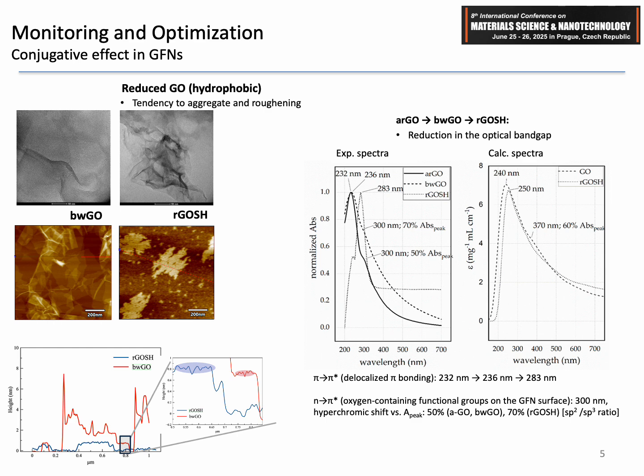This alteration, these spectral changes, can be related to two main factors: the formation of nanometer-size sp2 clusters and alteration in the linked chromophores, such as carbonyl or C=O instead of C-O bonds. What is more, the pronounced bathochromic shift to 282 or 283 nanometers that we observe for the reduced GO thiolated suggests the restoration of the pi aromatic domain, and the almost disappearance of this band is very well evident, as also paralleled by the comparison with the theoretical spectra calculated that we can see on the right hand side of the slides.